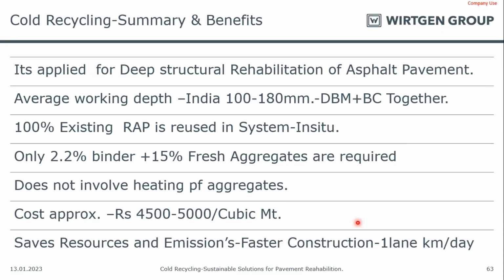So we only require an addition of 2.2% of bitumen as binder, VG30, and 10 to 15% of fresh aggregate as per the design. So here there is no heating of fresh aggregates. The approximate cost for this, including the machinery, is 5,000 rupees per cubic meter. So it's a faster construction, you get savings in emission, and roughly you can complete 1 lane kilometer per day.